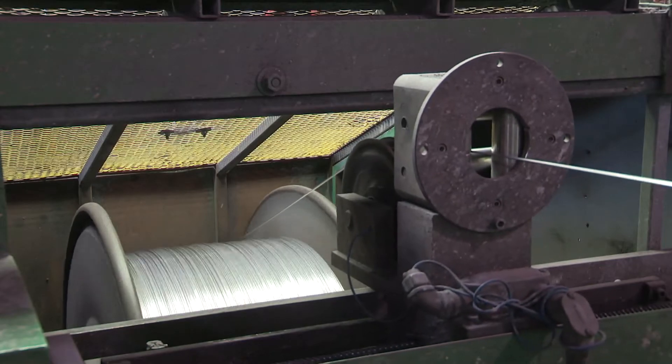As you're producing our product, it goes through a four-stage cleaning step at the end of the drawing operation. It's then further cleaned before the annealing operation, and that step is repeated every time it's drawn and annealed. With dirty wire, you build porosities and poor weld. So it's critical that you have a clean product going through the plant.